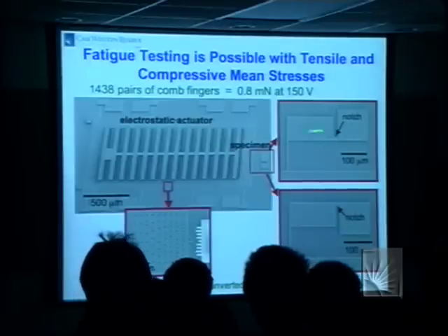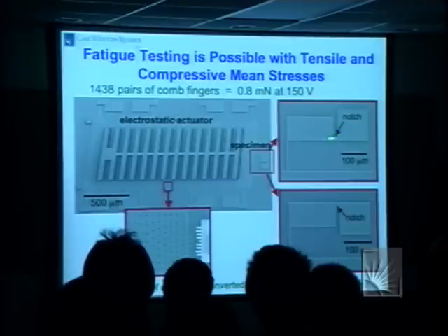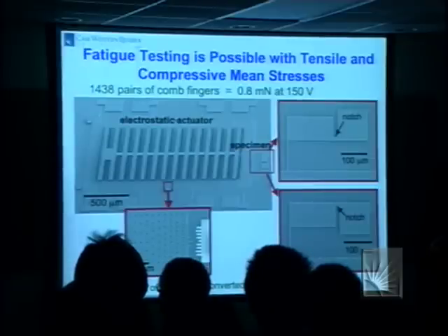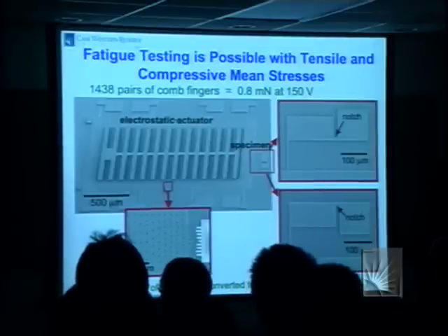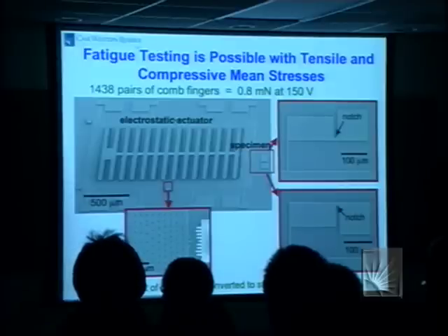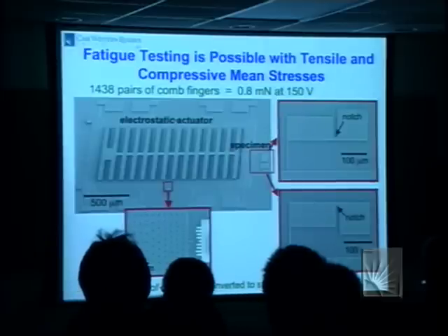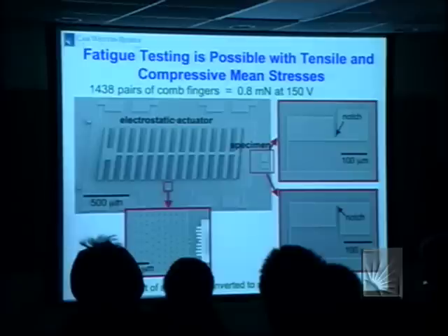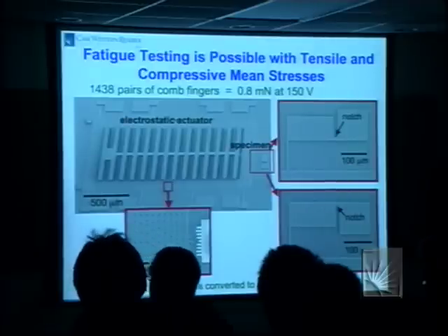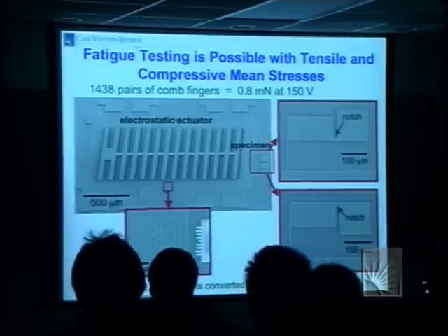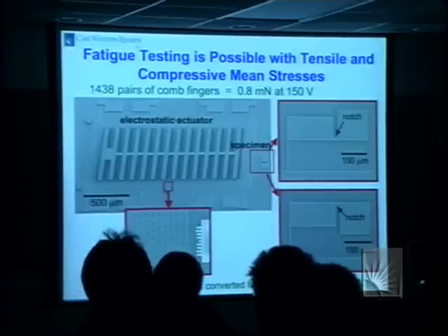And the important thing I show in these two devices, this is mostly the device we use, which would just create a tensile stress at this region of this micromachined notch. But we can turn this upside down. So how do we work this device? We put this device in resonance, and its resonant frequency is about 10 kilohertz. And then we simply increase the amplitude of the AC voltage until we get failure if we wanted to do a DC, a short-term test. But if we combine a DC bias as well as the AC alternating voltage, we can do experiments with mean stresses. And that turns out to be very useful in the experiment I'm going to show you. Again, essentially it would be impossible to do an experiment on a brittle material like silicon with both mean stresses and alternating stresses, but DC and AC biases make this relatively straightforward.